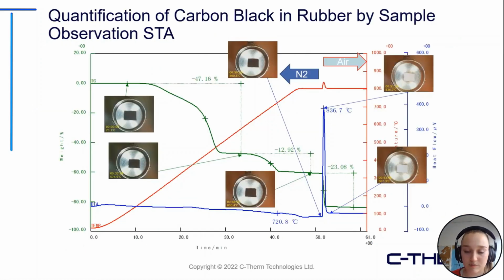So I'm going to start with the image this time and just give a quick annotation. So we started with the rubber sample. You can see on the left, we experienced some mass loss. The measurement is done in nitrogen initially, and you can see on the screen there at 800 degrees Celsius, we actually switched to air. So with the first 2 mass losses, we're seeing a decomposition of the resin in the rubber, and we're seeing a decarboxylation of the calcium carbonate or the filler in the rubber. And then when we switch from nitrogen to air, there we're seeing the loss of the carbon black.